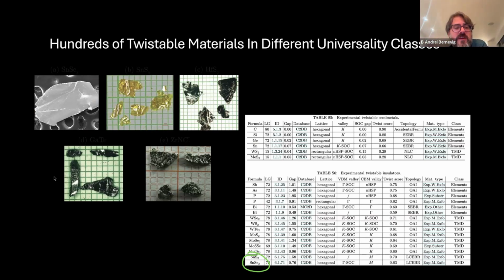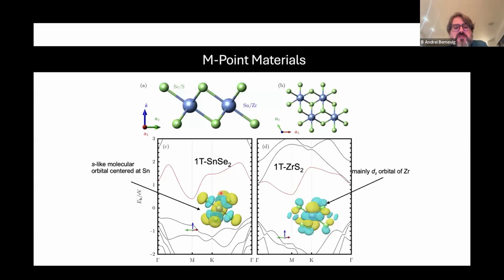They can then be exfoliated to single layer. Now, if I have this many materials that can be exfoliated to single layer, I can actually make twisted samples. I can take 2 layers and make homo, meaning the same layer, hetero, meaning 2 different layers, 2 different materials, etc., layers of twisting, and obtain different band structures. All I need in order to be able to predict things is to start with some nice band structure at the beginning. So for example, this is tin diselenide, and you can clearly see how it has a super nice band structure here at an endpoint minimum. Because the single layer has such a clean dispersion, I can hope that if I twist this material, I'm going to get a nice and clean dispersion.